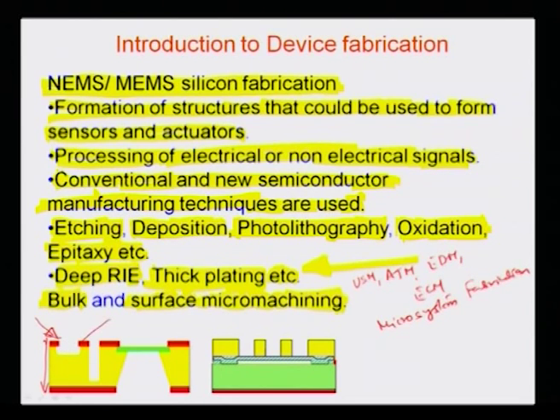So, there can be, for example, a protective layer here which you have etched out and created a small crevice or a cavity. Another example is this particular etch pit here, which is a high aspect ratio structure, and this can be obtained by a process called deep reactive ion etching, where the power of plasma can be used for driving atoms in a particular direction so that they can knock off the surface atoms here, and then based on that high aspect ratio structures can be formulated.